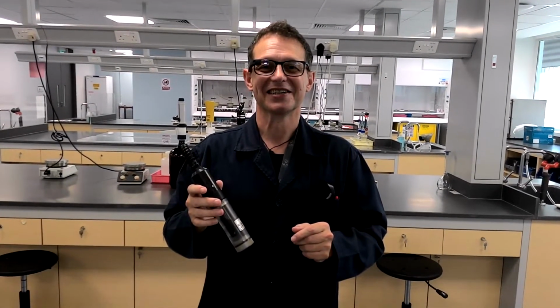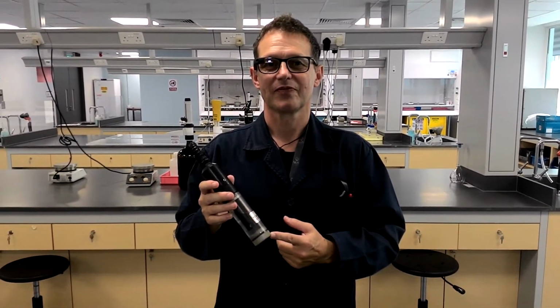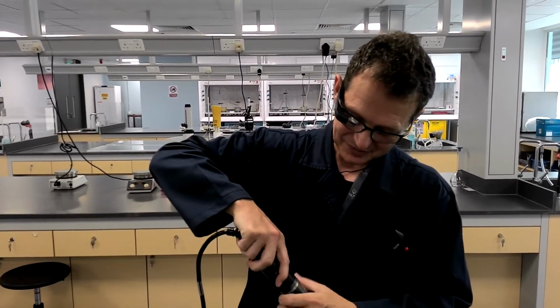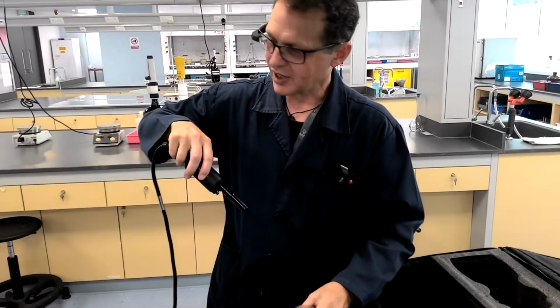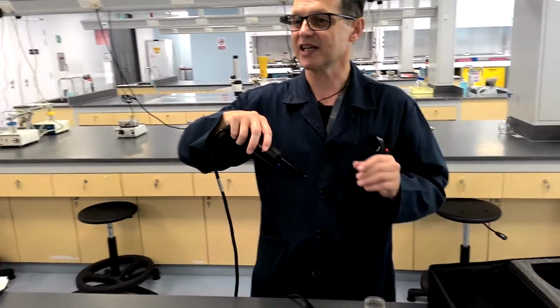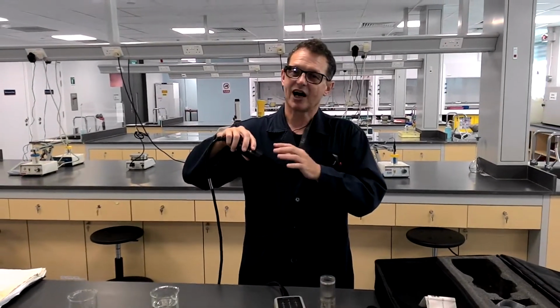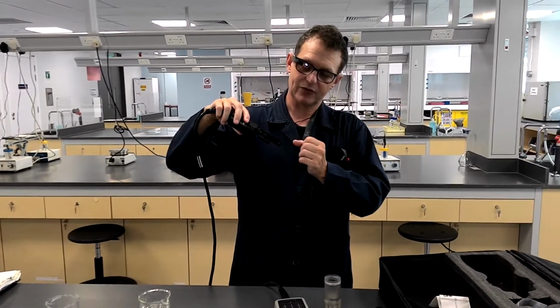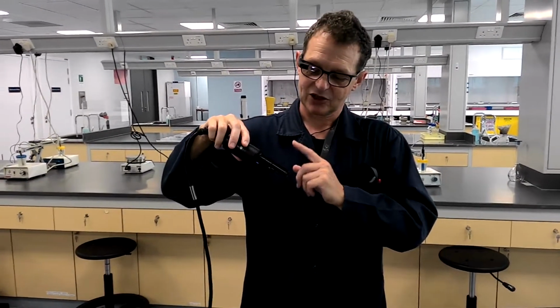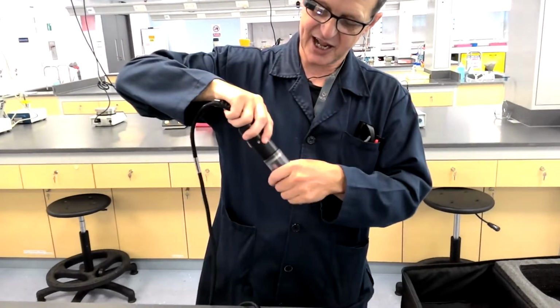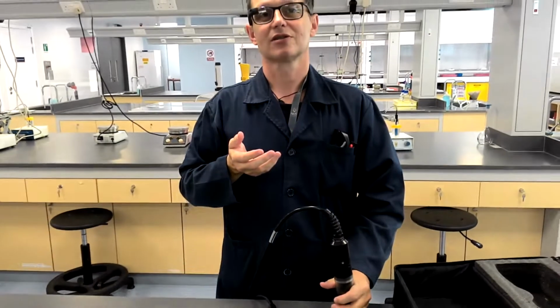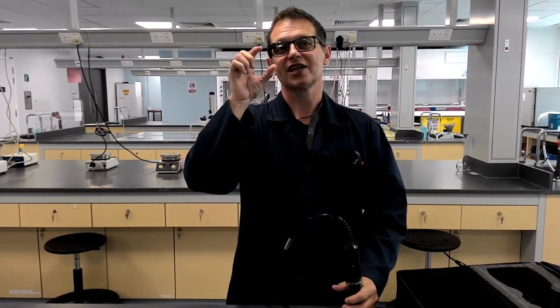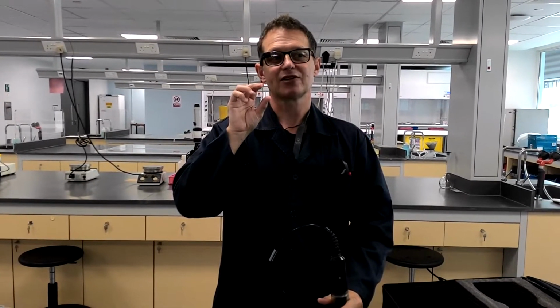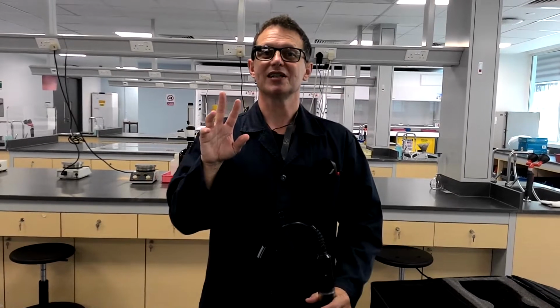All right. So if it was stored in air instead of saline, there won't be any diffusion of ions, isn't it so? Right. Then there's a different problem. I'm looking round to see, and I can't see any in the lab. Any laboratory, you'll find old pH electrodes, because if you store them dry, which you must never do, three things happen. The first is that the electrolyte will evaporate out of the electrode. And these electrodes are combination. You have a reference electrode inside the glass electrode. That prevents the reference electrode working. In fact, it destroys it, so that the potential difference that this probe gives from which we get the pH would be fairly meaningless.